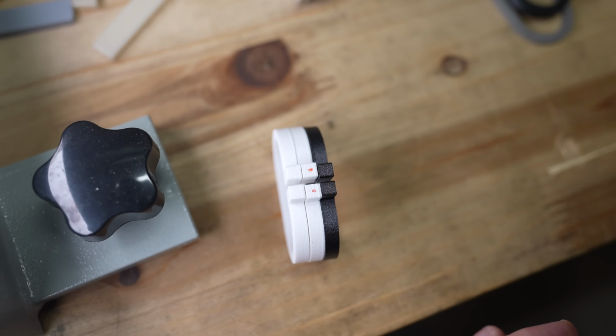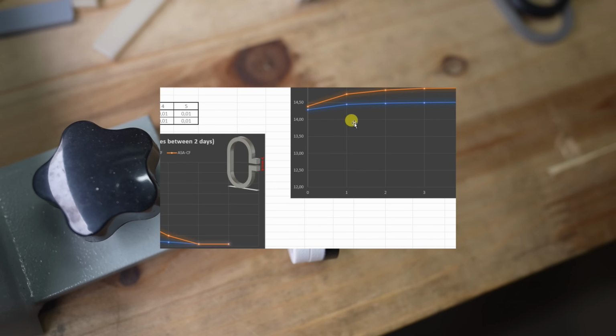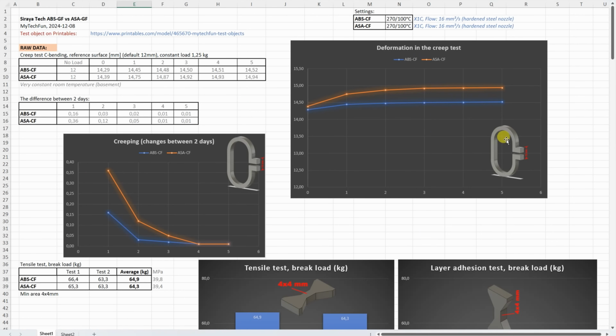After this test, almost no permanent deformation on them, but I can see slightly more deformation on the ASA part compared to the ABS. On creep test, this is the distance between two reference surfaces, and the smaller values are better, but this is only the bending. What we need is the difference between 2 days, that's the creeping. And here we can see that the ABS is slightly better compared to the ASA, less creeping, but in both cases these are quite good materials. I mean, only some minimal creeping on day 1, but after this the deformation was very minimal.